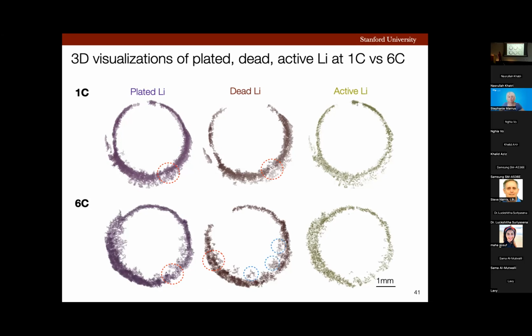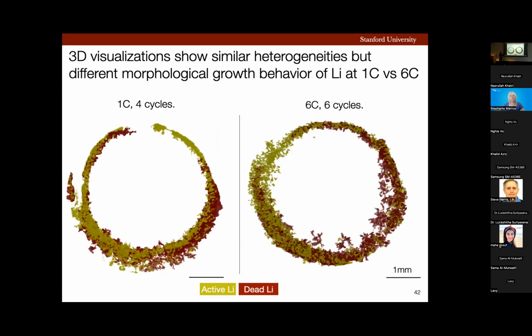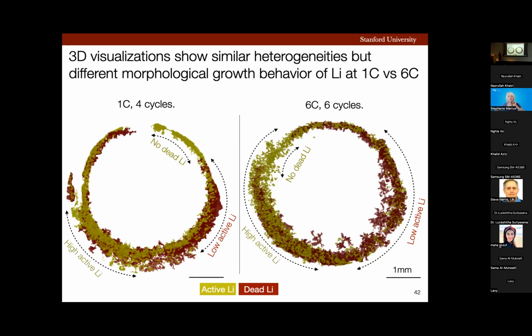At 6C, we also notice these tip growths, which are originating from the base of the root growing structure, which we didn't observe at 1C. Now, if we look at the dead and active lithium placed on top of each other in 3D, you can see that there are similar spatial heterogeneities in the behavior of lithium plating at both the charging rates. For example, first, there are regions that didn't form any dead lithium present at both 1C and 6C. There are regions that formed very low active lithium. We mostly see red here, right, which is dead lithium. And this is present in both the batteries. We see regions that formed very high active lithium present in both the batteries.